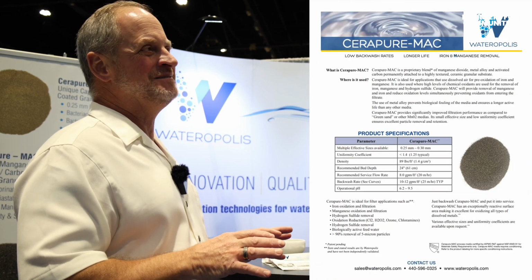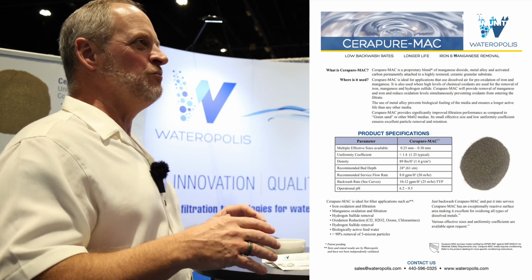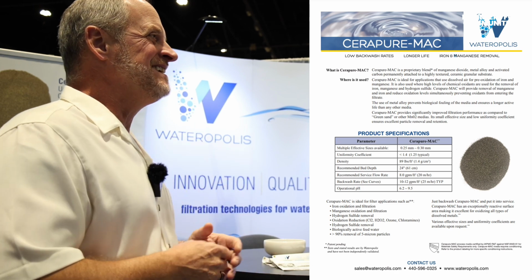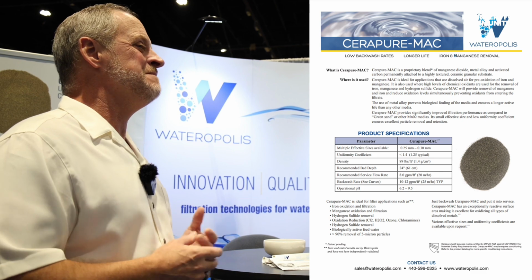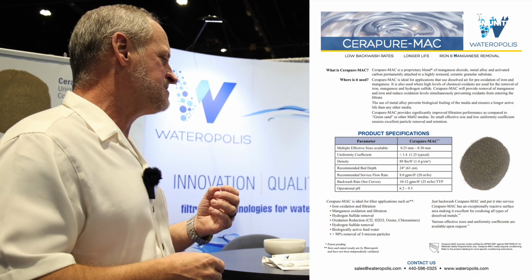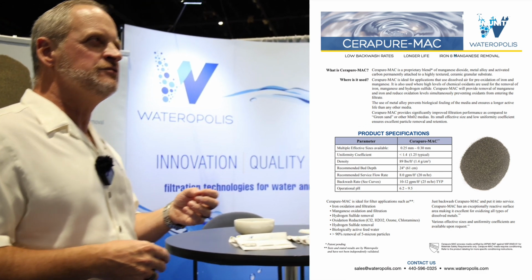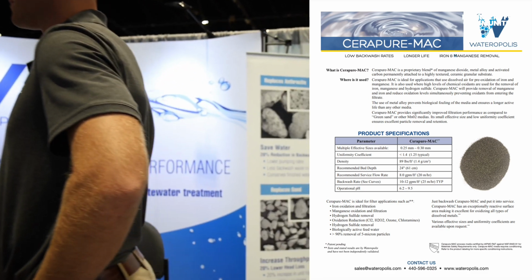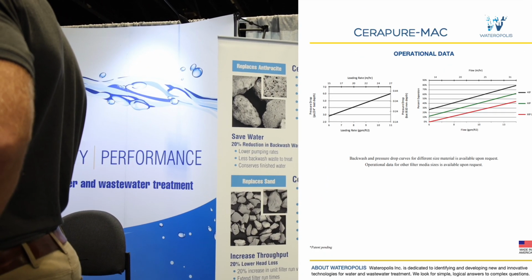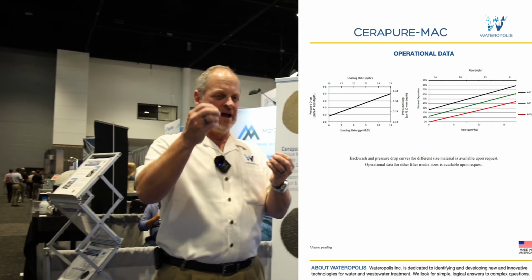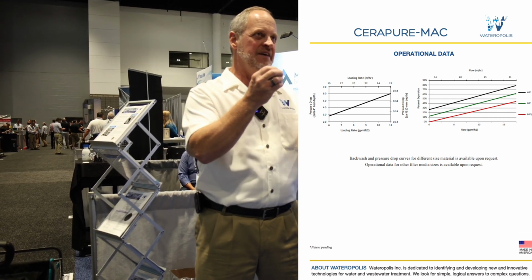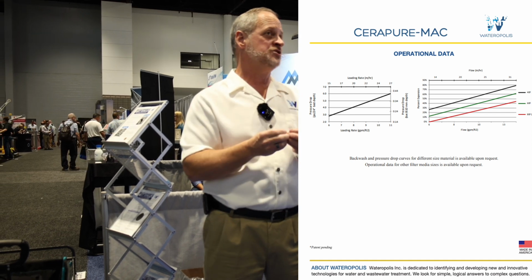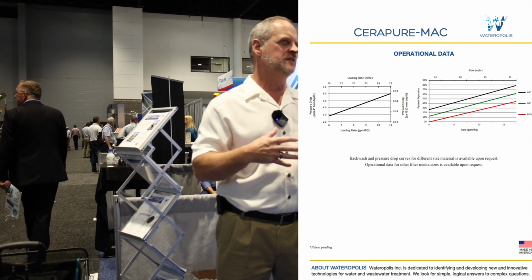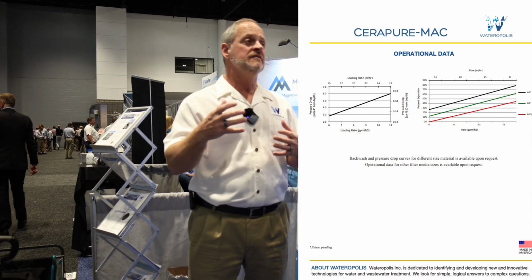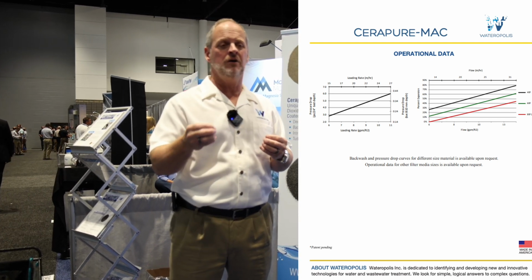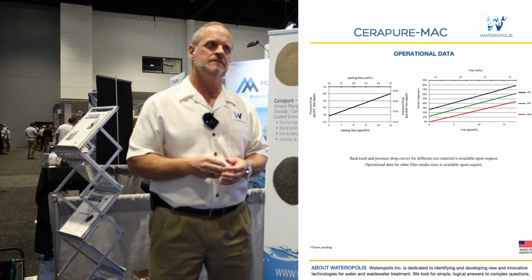Manganese is a little more difficult. Sometimes you have to stand on one foot, pat your head, and wave a magic wand, because manganese can be a little fussy. So we've learned how to optimize products and put a reactive surface on those products. Manganese often needs a catalyst. So you need an active surface, and the manganese has to react with that surface, and then you precipitate it on the media until you can backwash it out. So that's often a little different technology than we would use. That technology can be used for iron as well, but it's really suited for manganese removal.